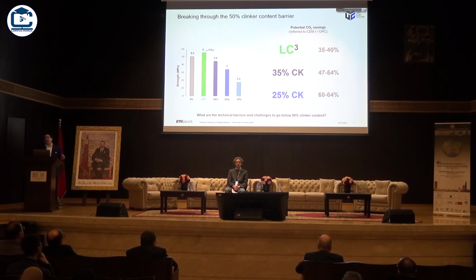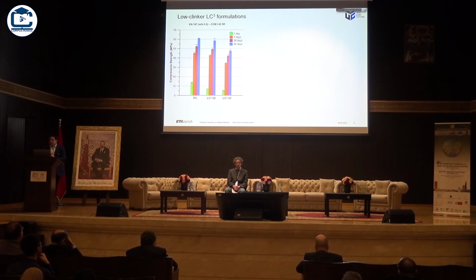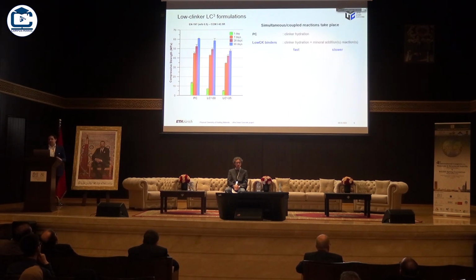And also, we haven't answered what the challenges and the technical barriers are to actually do that. Like, can we actually do it in a way that is reliable and makes any sense? In terms of strength, I'm showing you results of LC350, and on the right side you have LC335, so we're already pushed quite below the 50% clinker barrier, and you can see that the strength is actually not so bad, but it's certainly not the same strength level that we get with OPC. And we need to understand why this is happening.